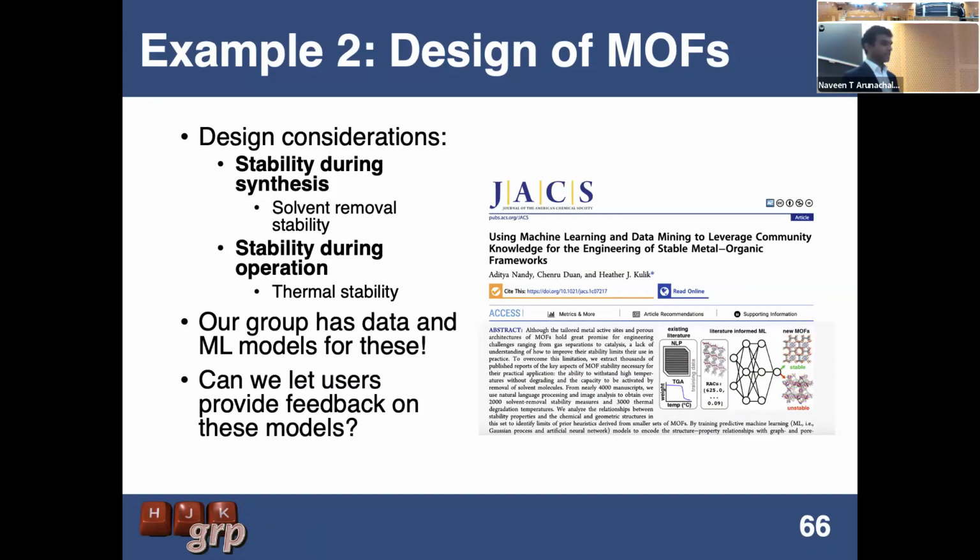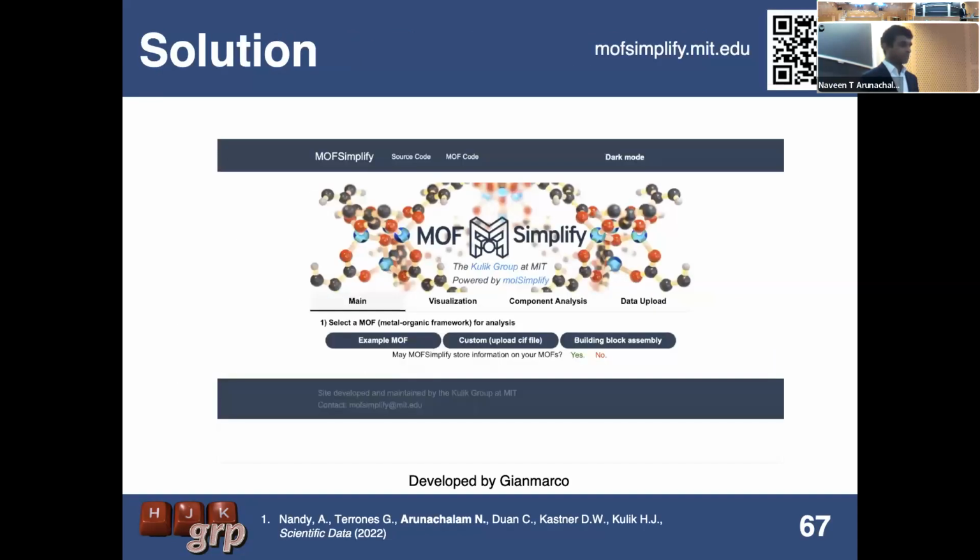When it comes to the design of MOFs, there are a few considerations. The first is stability during synthesis. We might look at the solvent removal stability, because you have to remove the solvents during the synthesis of MOFs, and if they fall apart during this process, then you just don't have a working MOF. Also, we're interested in their stability during operation. They're operating at high temperatures, and we don't want them to thermally degrade, so we want to look at their thermal stability. Our group has data and machine learning models for these properties. And the question is whether we can let users provide feedback in these models.